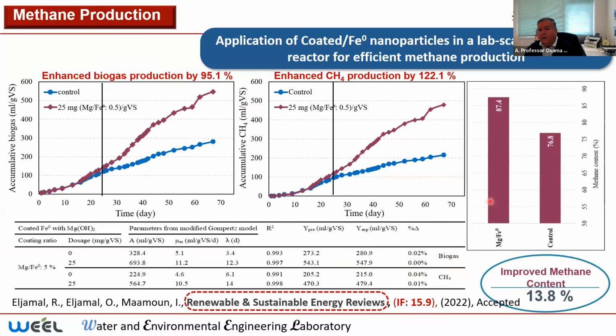So it was a very good achievement, using this coated iron nanoparticle to improve the methane production by more than 120%. For example, this figure shows how much the total biogas improved when we applied just 0.5 gram of the coated iron nanoparticle. We got an improvement in biogas production of 95% compared with the control or the normal system. On the other side, the methane produced from this system increased to 122% compared with the control. So this nanotechnology not only increased the biogas by 95%, but also increased the percent of methane inside the biogas by 13.8% compared with the normal way. So we were able to increase the total biogas, and we also increased the methane content.